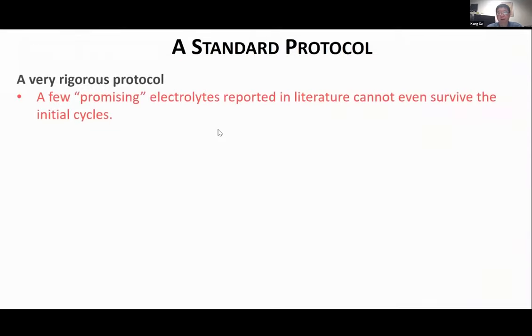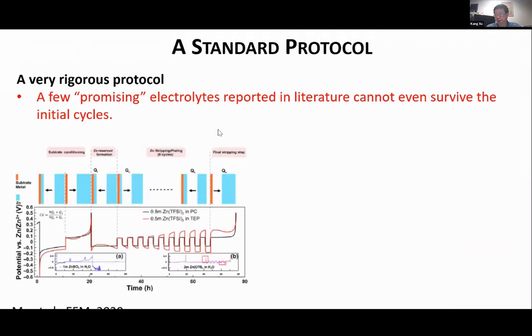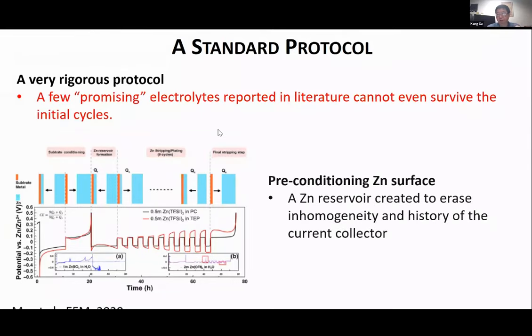This protocol was published already, and we use it to examine a few promising electrolytes already reported in the literature, not by our group, but by other groups. We found that quite a few of those promising electrolytes cannot even survive the first few initial cycles. In the initial cycle, we standardize the surface condition of the zinc surface by preconditioning, building a reservoir on a zinc-free anode cell. We know exactly the thickness and how much capacity is there as the only source for zinc cycling. By doing that, we make sure that all the electrolytes pass this rigorous test. And unfortunately, most of the so-called promising electrolytes cannot even pass a few cycles.